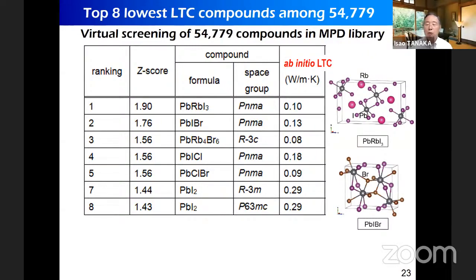We were very surprised to find that after validation by first principles LTC calculation, this is a quite lengthy calculation, but it is doable for 10 crystals. And we found that those highly ranked materials show quite low conductivity. Remember that our target was 0.1 watt per meter Kelvin. So those materials already showed quite low conductivity. So we were very happy with those results.